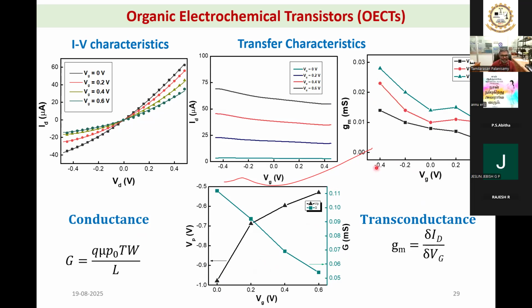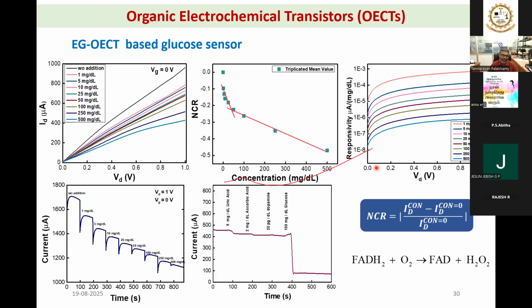So all these things are the typical characteristics of your OECTs. So the device works perfectly as an OECT. Now we can use it for biosensing purpose. And we have tested the device for different glucose concentrations, starting from 1 milligram per deciliter to 500 milligram per deciliter, and you can clearly see there is a gradual change in the slope. If you extract the value from this IV characteristics, you get a slope something like this.